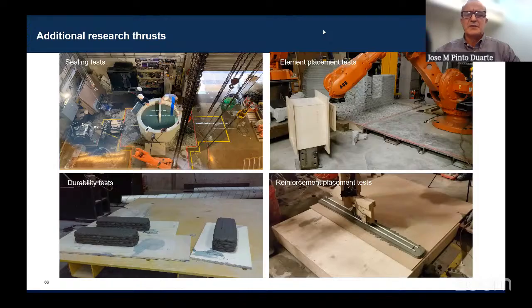And then you have to do durability tests. So basically, in the case of Alaska, we are working with the University of Alaska in Fairbanks. So we printed concrete parts, and we put them in artificial environments that simulate the freeze and thaw cycles that exist in nature. So basically, you go to a certain temperature, then you raise the temperature and go back down again, and so on, to see if the printed concrete is durable enough to withstand the rigors of the climate.